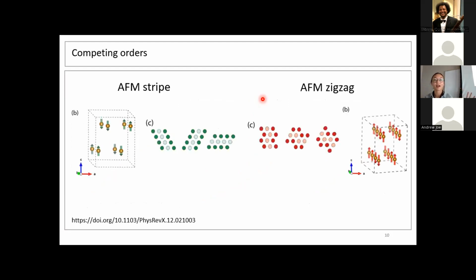Okay, so we have some collaborators who do neutron scattering studies. Neutrons are a really great way to study magnetic order because they have spin, but they don't have charge. And what they were able to see is that there are two different kinds of antiferromagnetic order in the system. Even though we have a triangular lattice, we know that the spins want to be opposite their neighbors. There's still a lot of room for what that can look like and what kind of patterns can come up. It turns out we have one which forms these little stripes. Here these dark circles are a spin pointing up, light circles are a spin pointing down,